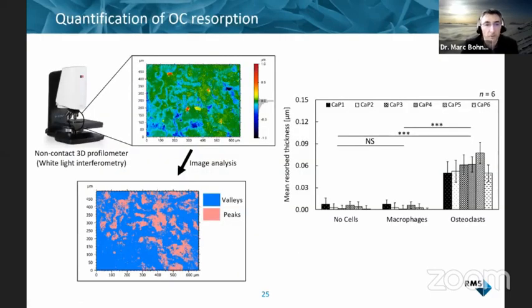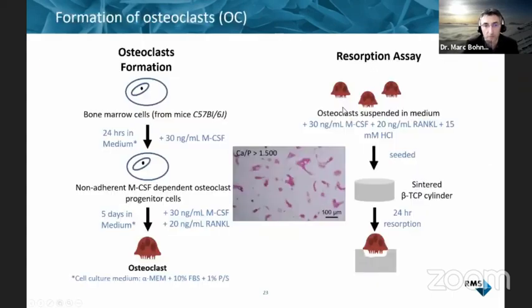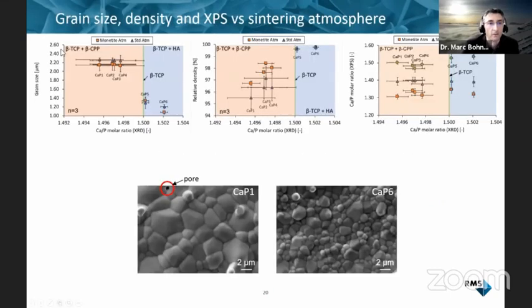The measurement of the resorption was done by profilometry. You see here on the image of the surface that you have an osteoclast that moved on the surface here, the same here or here. And we measure basically the volume of material that was removed, and we normalize it to the surface of the material. So we obtained a mean resorption thickness. With no cells or macrophages, nothing really happens. And it's when you add the osteoclasts that you see resorption happening. There are 6 different bars in the histogram because we used these 6 different materials. And just to remind you, let's quickly go back here. So this corresponds to this beta-tricalcium phosphate material.